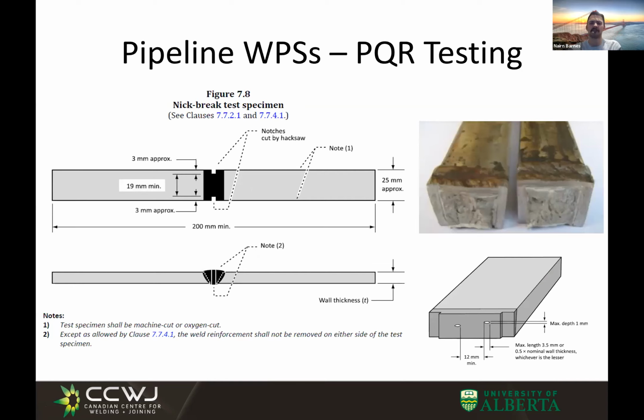Nick break testing is a very specific test to pipelines. I don't really know that you'll see it too many other places, but essentially you prepare your sample, which is more or less a rectangular prism with a weld in the middle of it, and then you're going to notch it on both sides. So you machine it down and you notch it.